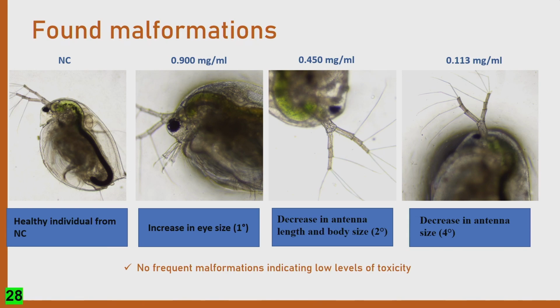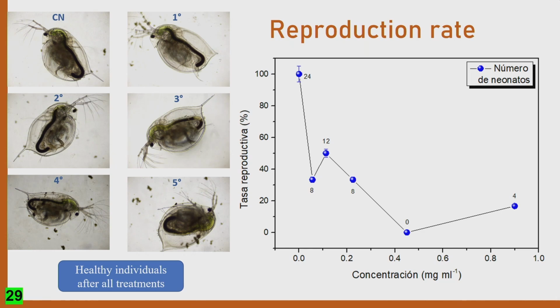And where we found malformation, it is also increase in eye size. We can see it's not significant, but some stress can be induced in the Daphnia magna. And at the other concentration, we get a decrease in the antenna, where the analysis was more significant, statistically speaking.